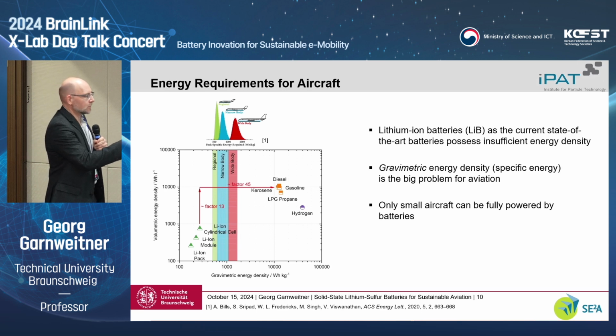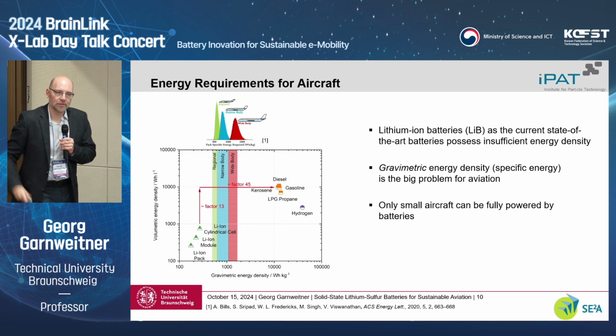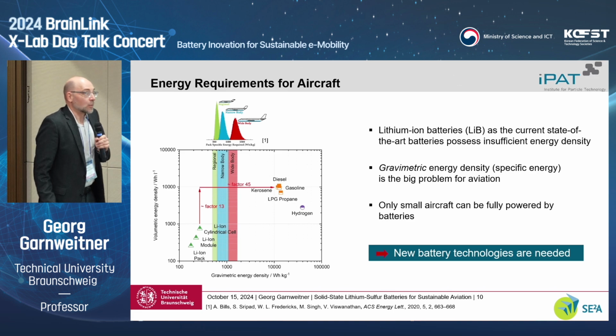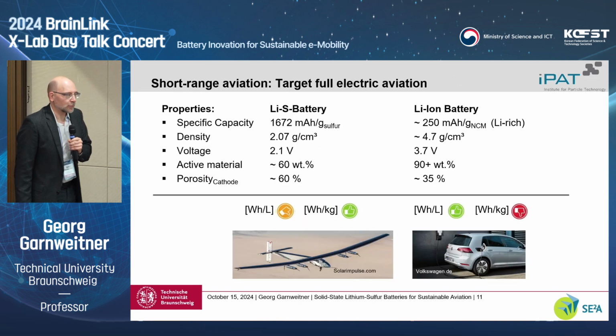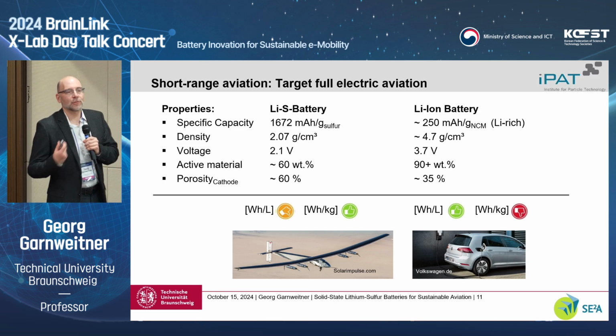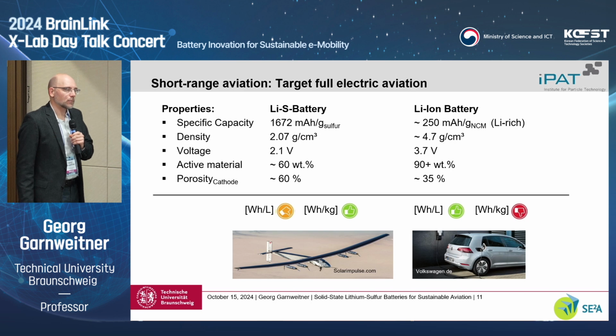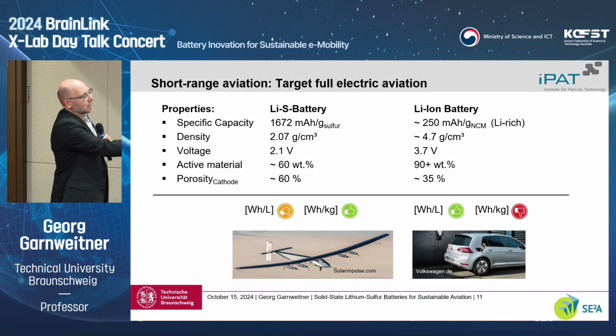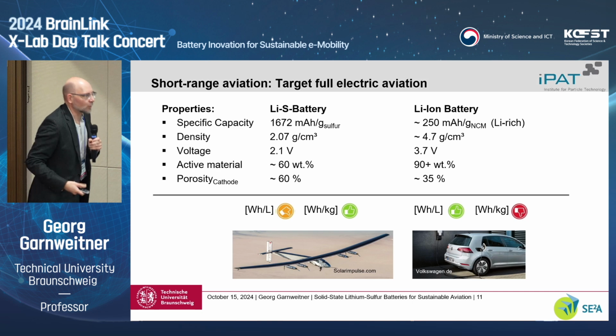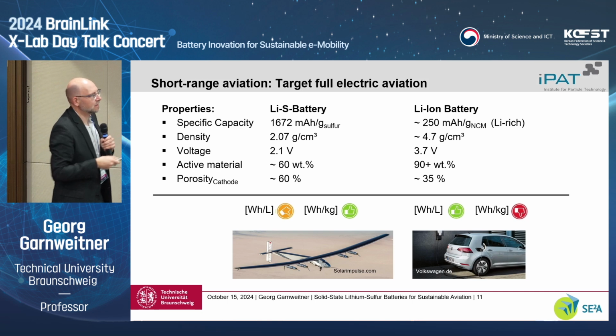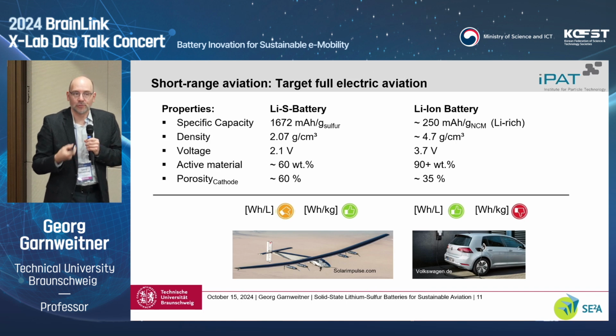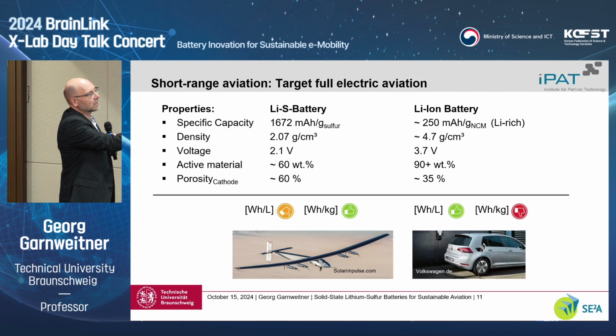And of course, we see also that the big problem is with the specific energy or gravimetric energy density. Here we have the largest difference that needs to be spanned. So we need new battery technologies, and we decided to focus on the lithium-sulfur battery here, because for aviation it seems more attractive than the lithium-ion battery. So basically the volumetric energy density is quite good for a lithium-ion battery, but we have typically a weight problem. And for the lithium-sulfur battery, it's kind of the other way around. So yeah, you have a larger volume. Partially, this is also due to the lower density of sulfur, but we have a very attractive gravimetric energy density, because with sulfur we can store a lot of energy.